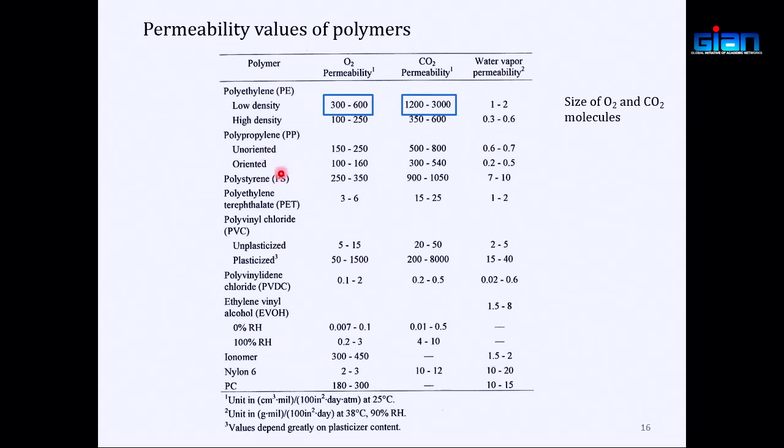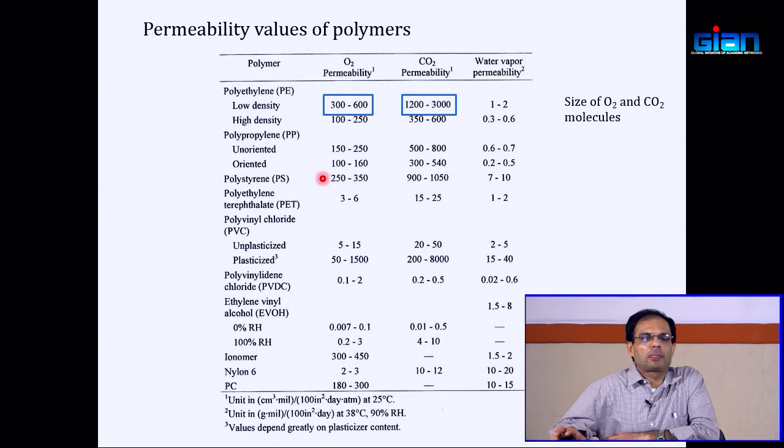Now this table is showing you some of the oxygen permeability and CO2 permeability and water vapor permeability of different films. I want you to look at it, that for polyethylene, the low density polyethylene, oxygen permeability is lower than the carbon dioxide permeability.